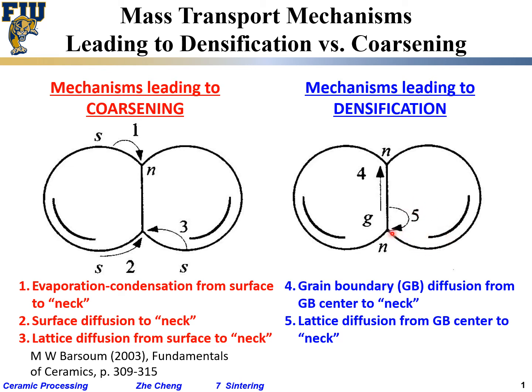With these two mechanisms, if you imagine the material that is initially at the grain boundary center moves towards the neck, what happens to the two particle centers? If the material moves from there to the neck, the distance between the two centers decreases — they actually come together, because the material that resided there is moving away. Of course the two particles would come together, and this is what leads to densification. The particles come closer together, and that's how you eliminate porosities.